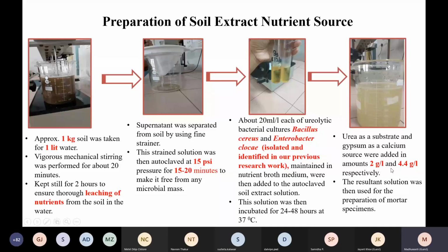Now, why were these concentrations decided? 2 grams per liter was picked up from our previous studies in which we got 2 grams per liter as the optimum concentration of urea in biocementing experiments, and 4.4 grams of gypsum for 2 grams of urea was decided as per the stoichiometry of the chemical reactions involved. Now what does the resultant solution contain? It contains these two bacteria with nutrients from the soil extract, and it now has urea as a substrate, and it also has a calcium source, that is gypsum.